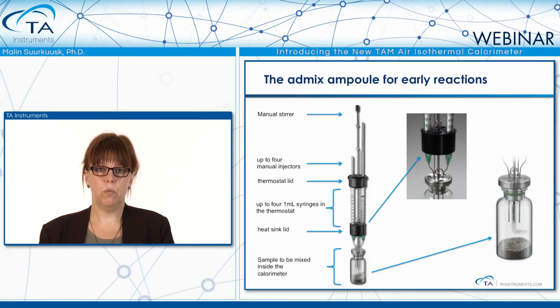The syringes, which could be 1 up to 4 1 milliliter syringes, sit in the thermostated part of the thermostat, and then you have a thermostat lid above the syringes. In this way, the liquid you're injecting into your sample is at the same temperature as the sample inside the calorimeter. Above the thermostat lid, we have the manual injectors, where you can push down to inject the sample into the ampule. And in this picture, we have a manual stirrer, and that can move up and down and also rotate, so you can get a very good mix of a cement sample. The motor mixer will just be rotational stirring if you put the motor on the top. And the height of the stir can be modified to fit that particular sample.